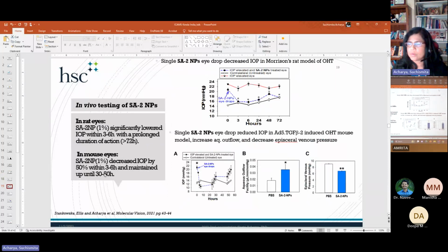And next, we did two experiments. One is called Morrison's rat model of ocular hypertension. What that does is you inject a hypertonic saline into the episcleral vein of the eye, which increases the pressure of the eye. So that's what you see in the red line. And then when we added our SA2 nanoparticle eye drop, you can see the pressure goes down almost to the baseline and stays there for longer than 72 hours, 3 days, with just one eye drop.